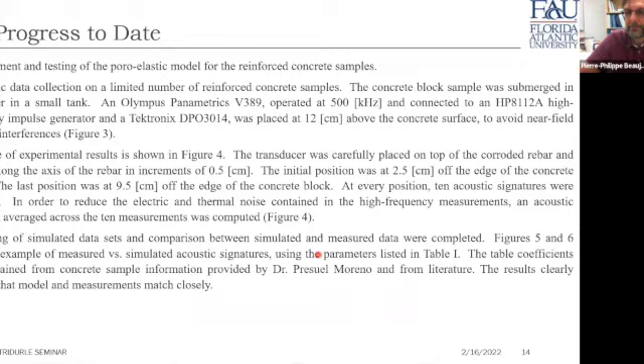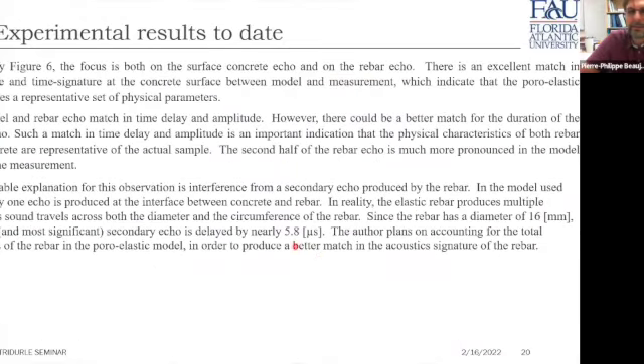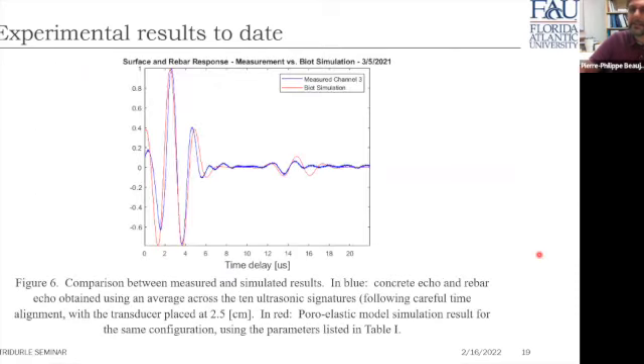So let me just go back to my comments over here. In the model used here, only one echo is produced at the interface between concrete and rebar, when in reality, the elastic rebar produces multiple echoes, as I just explained, as sound travels across both the diameter and circumference of the rebar. Since the rebar has a diameter of 16 millimeters, the next and most significant secondary echo is delayed by nearly 5.8 microseconds. Now, in addition to the work we are currently doing, we plan on accounting for the total thickness of the rebar in the Poro-Elastic model in order to produce a better match in the acoustic signature of the rebar. But still, as is, the match between the measurement and the model is of sufficient quality that we should be able to identify early cracks as they form.